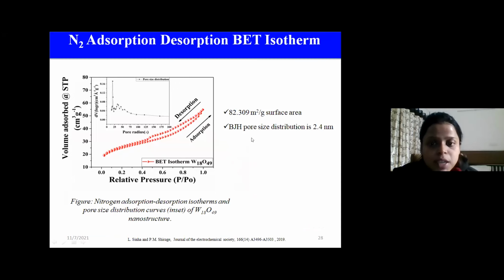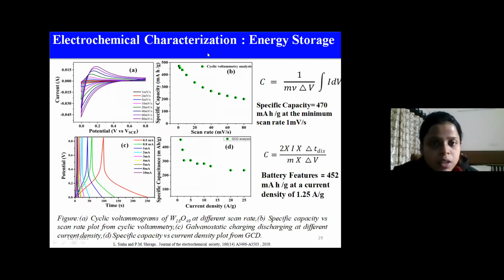So this is the BET isotherm, and it is showing that the material is giving a high surface area of 82.309 meters square per gram with a pore size distribution. This distribution is due to 2.4 nanometer. So this is the first we have done. We have used this material for the energy storage supercapacitor application.